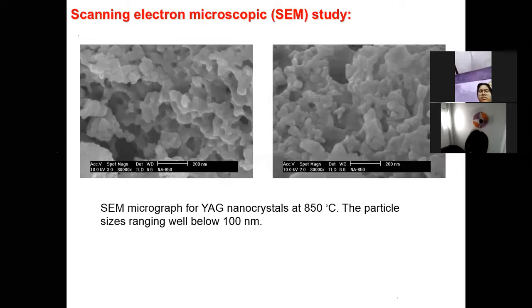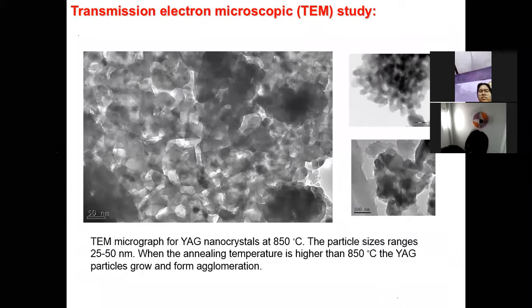So we use X-rays, then EDAX, and then the micrograph also shows whether the size of the crystallites is of the order of nanometers, that is down to 100 nanometers or so. Then only it is useful. So it is well below 100 nanometers. And then the transmission electron micrograph again shows the size. Here we see that 25 to 50 nanometer nanoparticles have been achieved when we anneal those materials up to this temperature.